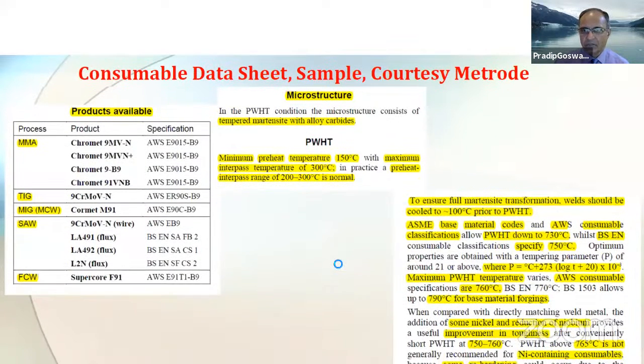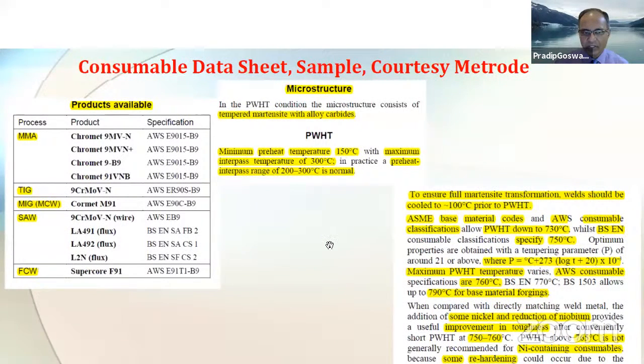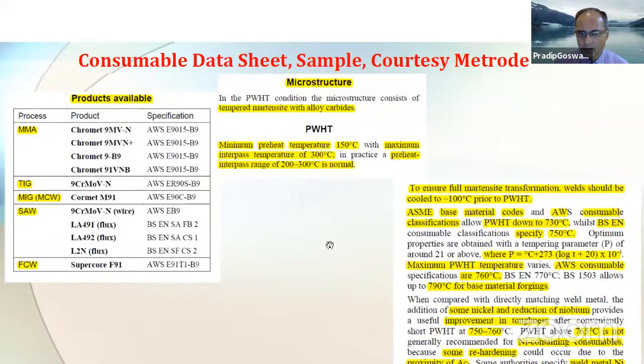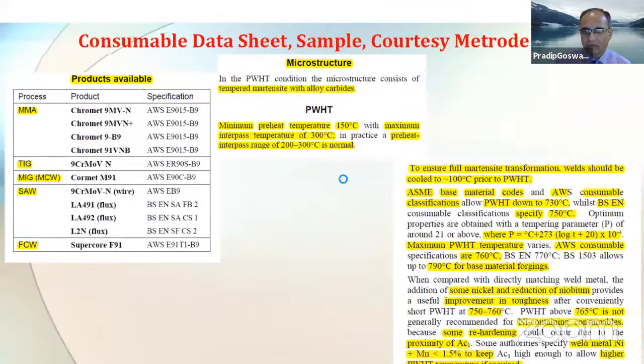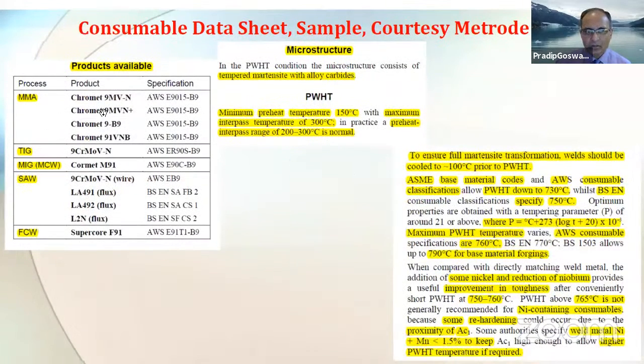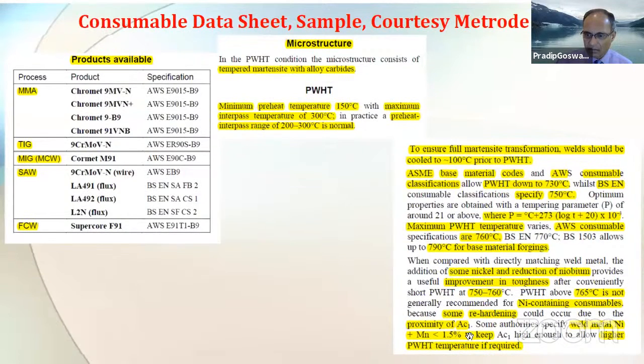These are quick snapshots from different consumable manufacturers. This I extracted from the manual or product catalog of Metrode. It talks about their products, typically what microstructure one can expect, what the typical post-weld heat treatment conditions are, and what the typical preheat and interpass temperatures recommended are.